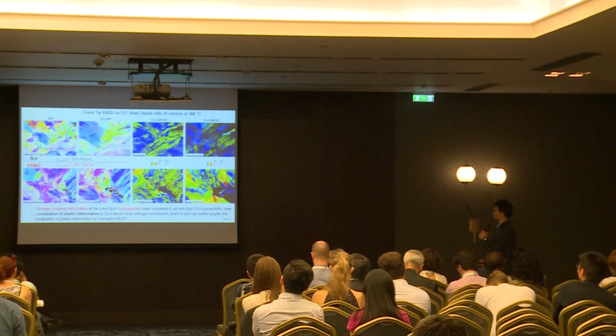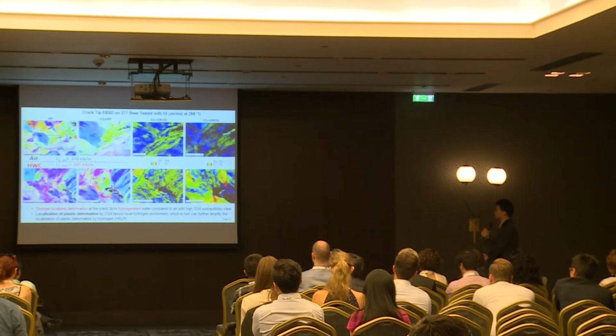We were also very curious about the microscopic deformation ahead of the crack, the plastic deformation. So we performed EBSD characterization. The upper four figures were for the test conducted in air. The lower four figures were the test conducted in hydrogenated water chemistry. And you can clearly see that ahead of the crack in hydrogenated water chemistry, we have found a lot of massive tiny grains, which were due to the localized plastic deformation. And also the average grain misorientation deviation was higher in the hydrogenated water. So this means there's a stronger localized deformation in hydrogenated water chemistry, and this was due to the synergy of DSA and hydrogen.